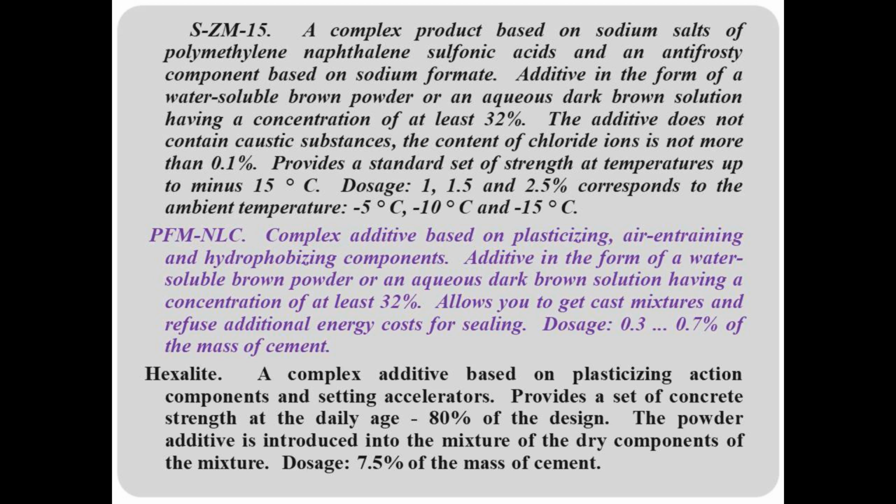Hexalite. A complex additive based on plasticizing action components and setting accelerators. Provides a set of concrete strength at the daily age of 80% of the design. The powder additive is introduced into the mixture of the dry components of the mixture. Dosage 7.5% of the mass of cement.